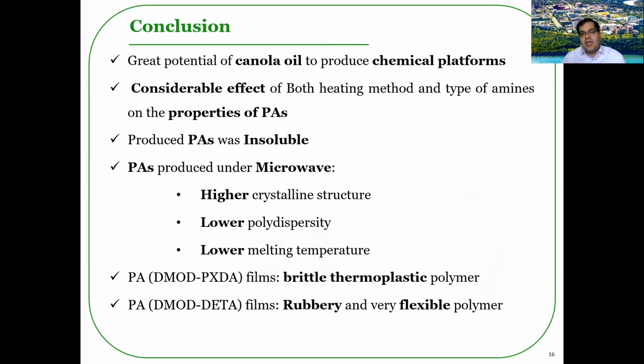As a conclusion, we can say that the canola oil had a great potential to be used for making different chemical platforms for the polymer industry. Both heating method and type of amines have a significant effect on the properties of the polyamides, which are not soluble even in the strongest solvents for the polyamides like HFIP. Microwave irradiation can produce polyamides with higher crystalline structure, lower polydispersity, as well as lower melting point. The semi-aromatic polyamide films were brittle thermoplastic polymers, while the linear polyamide films showed the characteristics of a rubbery and very flexible polymer.